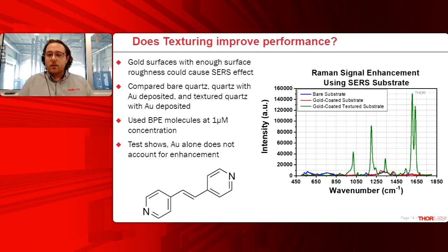So in this case, some of you may be asking, is the texturing actually improving the performance, or is it just surface roughness? This was a question I've gotten a few times, and that's because some of the original SERS substrates that were developed decades ago were actually based on just roughened metal surfaces. So to understand this point a little bit more, we ran an experiment where we compared a bare piece of glass to a gold-coated piece of glass, and then a gold-coated piece of glass that had been textured previously. And what we did find is that only the gold-coated textured substrates produced a good Raman signature, a good SERS signal.